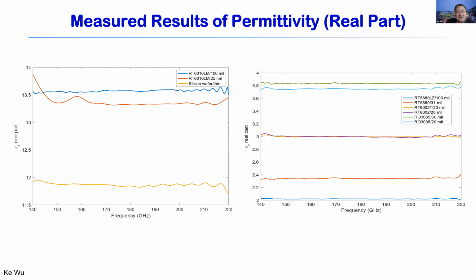And this also gave us the different Rogers substrate values. You can see Rogers substrate RT values, about 13.5 here, and also another value here. There is some variation at the border of the frequency range here. Of course this is partly because of the calibration or the measurement setup itself, which is not really valid over this frequency range. But it actually gives us quite stable values for the real part of the complex permittivities. So we are very satisfied with those results.